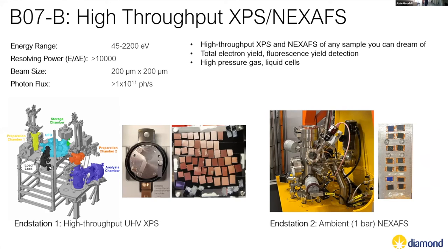121. One issue with resonance spectroscopy: you're tuning your photon energy to exactly the separation in your energy levels, and you go up orders of magnitude in terms of cross section. What that means is you generate an awful lot of electrons in your sample, and an awful lot of secondary electrons, which do a lot of changes to your sample. So you have to be very careful there.